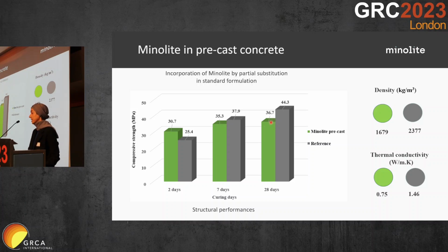For example, after 28 days of curing, we have 36.7 megapascal, while the normal one has 44.3 megapascal. But if you look at the density, you can see that the density of Minolite is significantly lower. And if you look at the thermal conductivity, it is 0.75 for Minolite, while for the normal concrete it is 1.46.